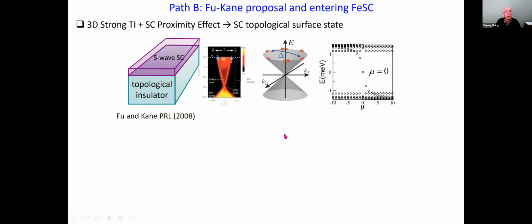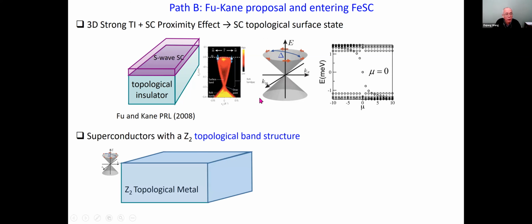And this is indeed what's behind the proposal of Fu and Kane that Vidya just talked about. You need a 3D strong TI with topological surface states, the helical Dirac cone, proximity effect coupled to an s-wave superconductor, and that will present to you a zero-energy state as a vortex core state. However, this discussion also motivates a general perspective of this physics, that what we need really is one superconductor. We don't need a hybrid structure.